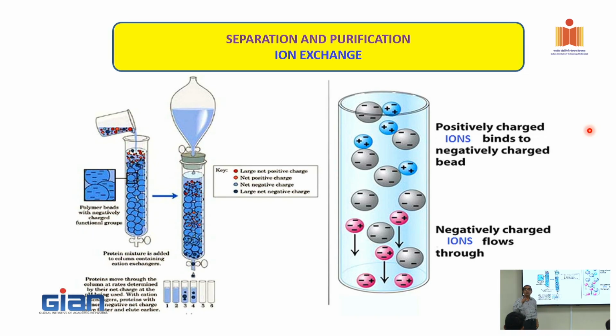So that is why loading capacity is significantly important. Higher the loading capacity, higher will be the enrichment ratio, and better will be the effectiveness of the resin. So before we actually choose a resin, we have to develop the loading curve. Not only the loading curve, we also have to develop the elution curve, because okay, it loaded, but I want 100% elution also. If it is not able to dissolve 100%, then what will happen? You are losing some material here. So the choice of the ion exchange resin should be in such a way that it has good loading efficiency and equally good eluting efficiency. That is good adsorption and good desorption.